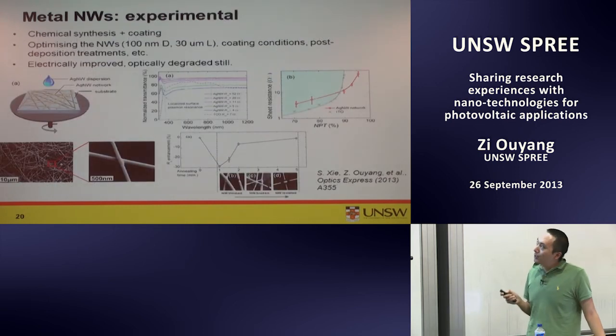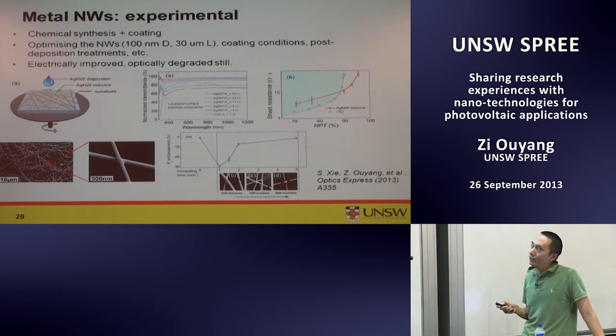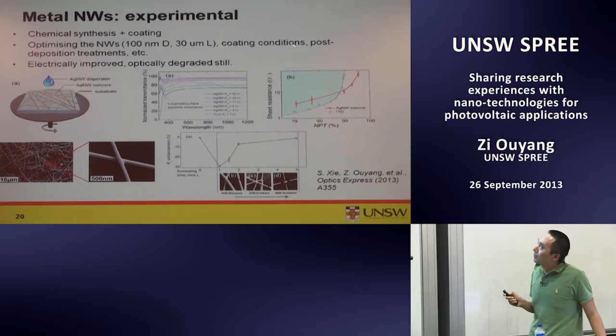So what we do is we have a chemical synthesis of nanowires in the dispenser, and we put it on the top of the substrate, spin coating or whatever, spray on, and then we have it on top automatically. So then we did some optimization of the nanowire diameter and length and coat conditions, and on glass we actually achieved, for some part, better result than the widely used ITO material.